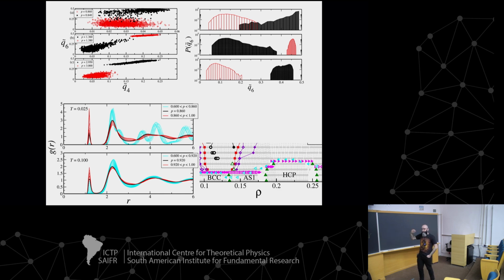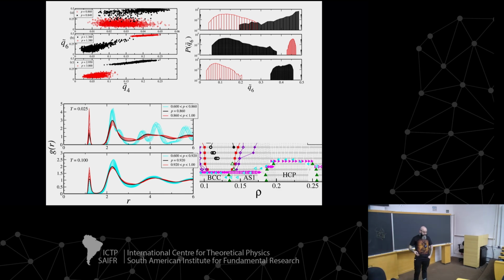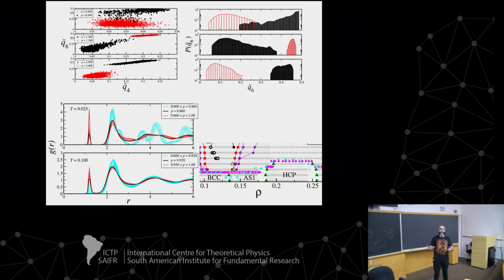Our guess, which the reviewers and the editor accepted, was that these anomalies in this behavior all start with this amorphous clusterization in the solid phase. And we did not observe this amorphous clusterization in the other phase transition. So we actually have this competition between a fluid with a BCC-like structure and another fluid with an amorphous-like structure. And obviously this is not the Widom line, because the system does not have a critical point, but it's a similar signature.